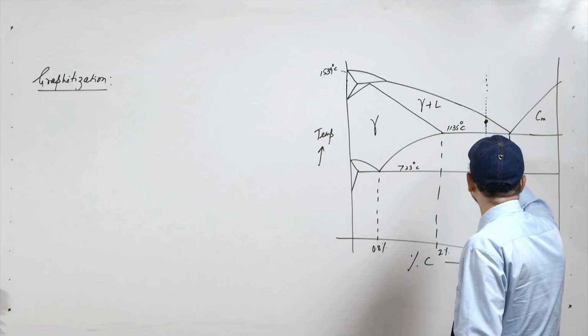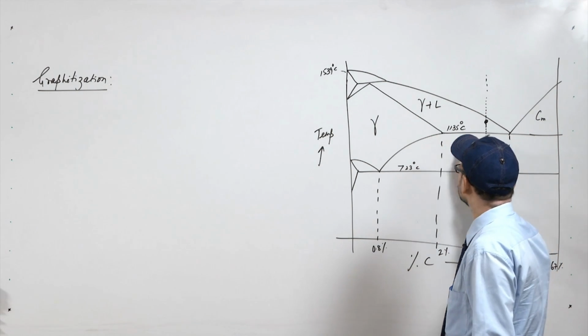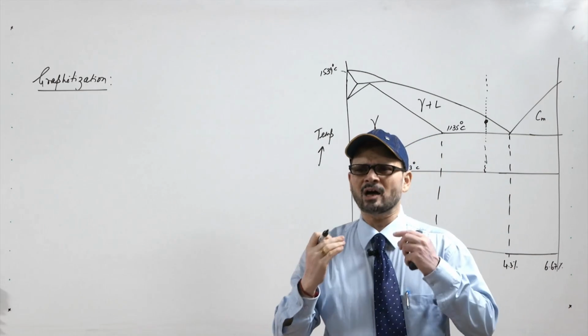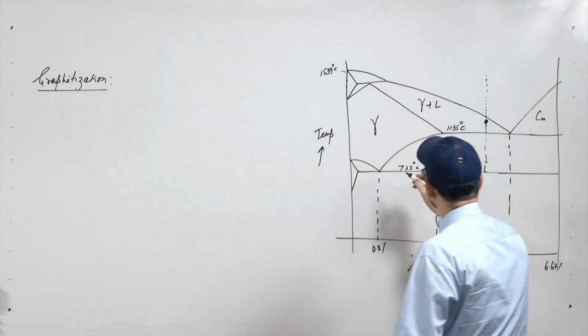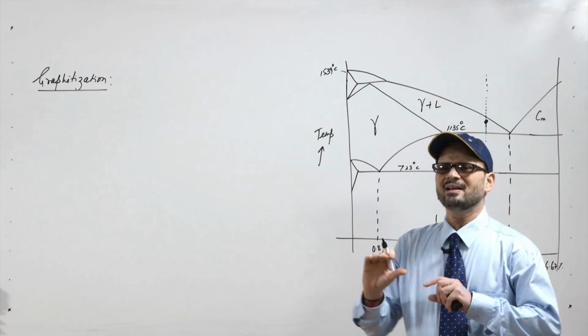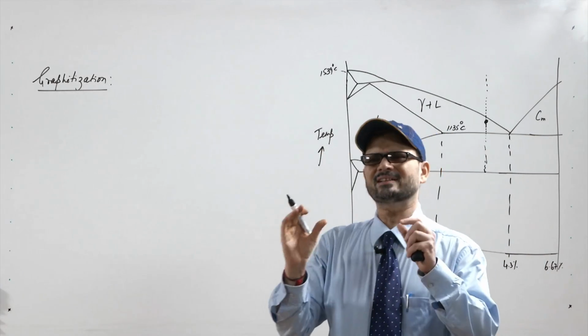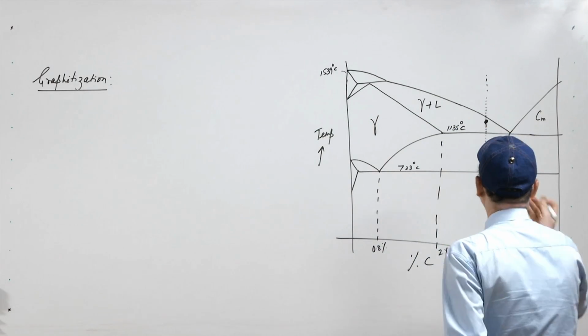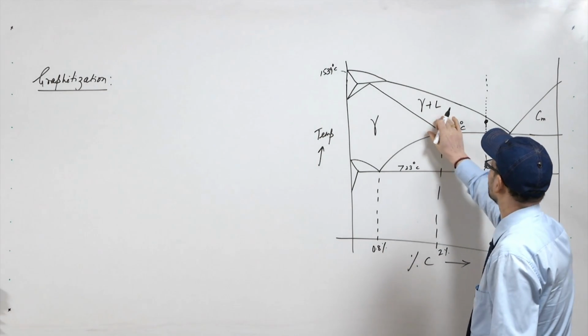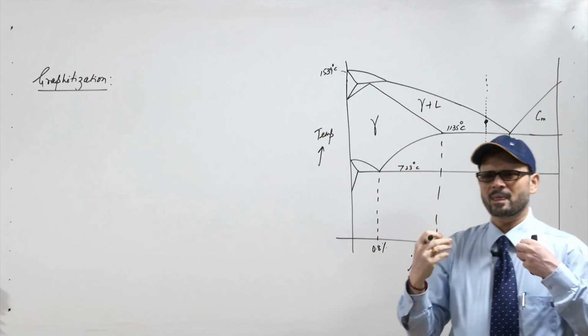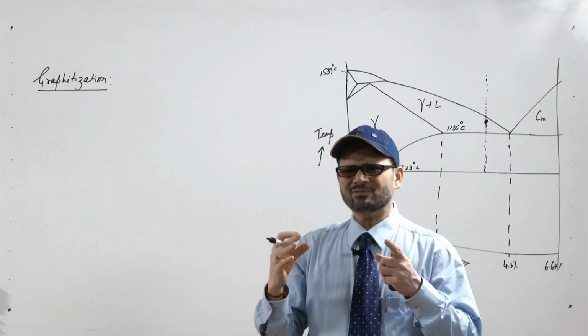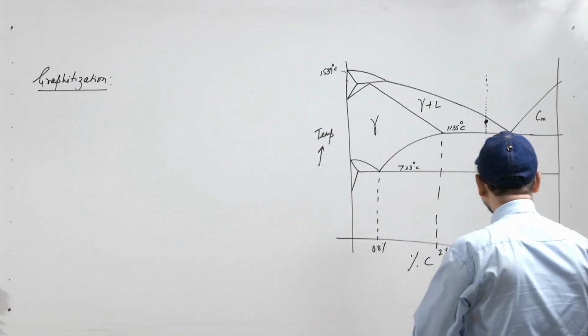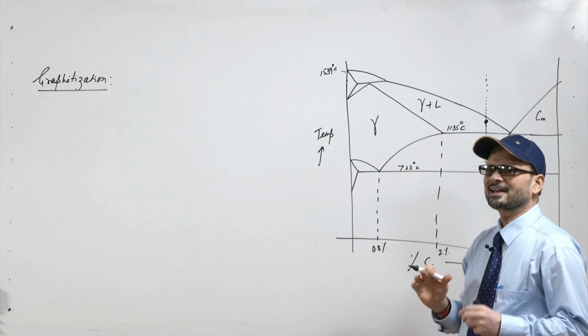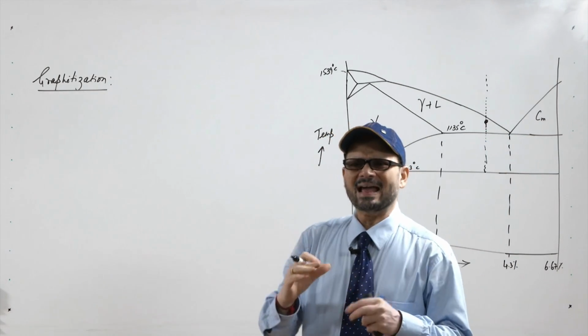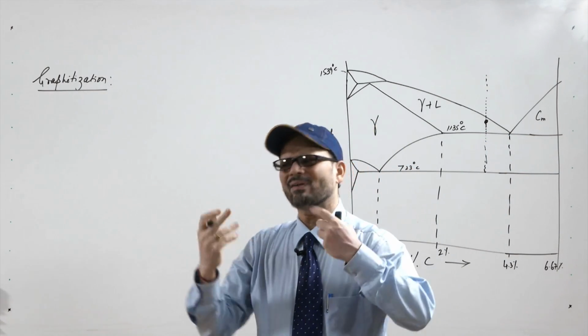So, once it comes to this line and touches this line, the austenite which was there will be losing the carbon, and maximum it can have 0.8% of carbon. So, it will be somewhere close to 0.6 to 0.8% of carbon it can maximum dissolve. All the carbon which is extra will be left by this austenite. Now, this carbon once it goes, it may appear either as combined form or as a graphite form.